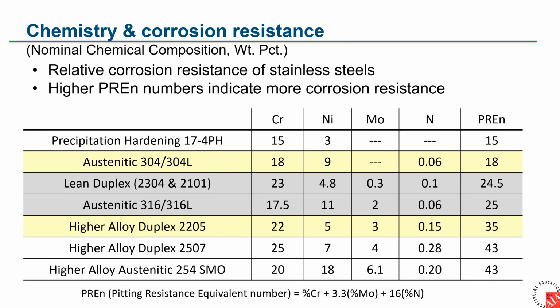Alloy 2205 is at 35. So again, a big jump up. 2205 is becoming far more popular, and the duplexes are in all of the new structural specifications or revisions that are in process. And we can go all the way up to the 40s. Stainless steels that can be immersed in seawater without corrosion or aggressive process streams.